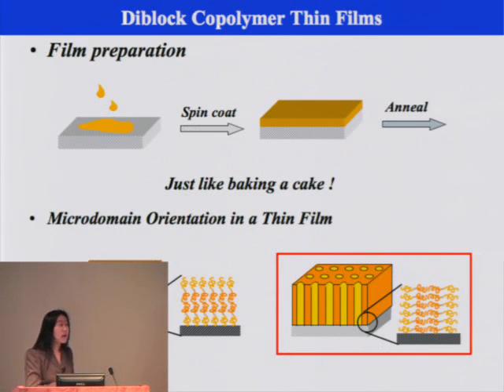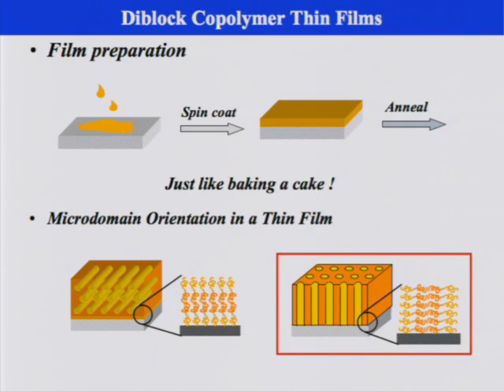So how are you going to use it? It's very simple, I call it just like baking a cake. You have a polymer, and you dissolve it in solvent, oftentimes those are organic solvents. Then you spin cast it, just like making a crepe. You put it on a substrate and let it spin. The solvent evaporates and you have a smooth, thin film with controlled thickness. Then subsequently, you put it in the oven or under solvent, giving the polymer a little bit of mobility so they can do their own magic and start to self-assemble.